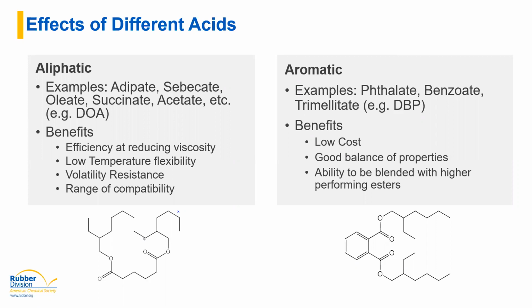And the other nice thing about aromatics is that you can blend them very well with higher performing esters. You might find an ester that solves all of your problems and does everything incredibly well because it's such a high performing material, but it's too expensive to actually be used practically. A lot of times aromatics can be used to blend with those that give good compatibility and help to not dilute down the performance too much.